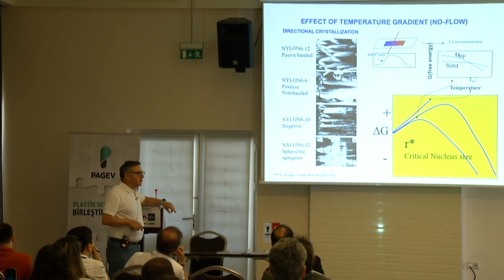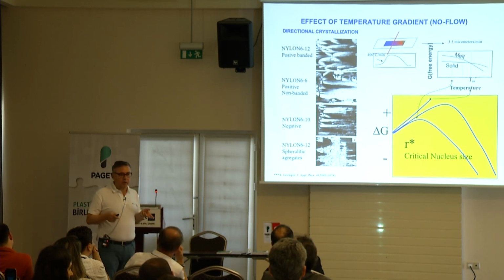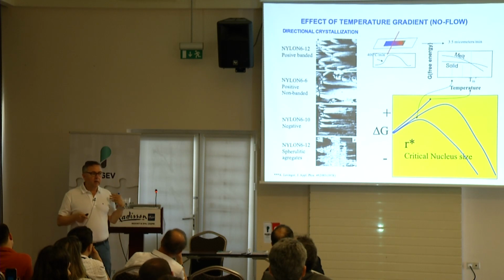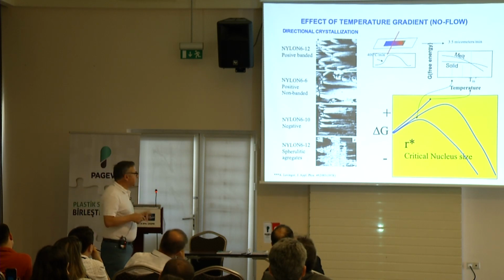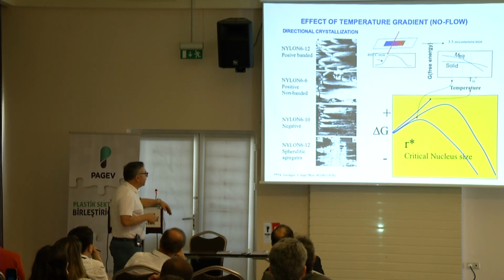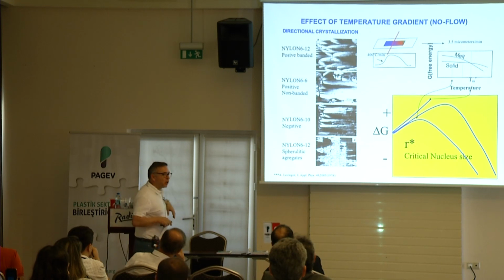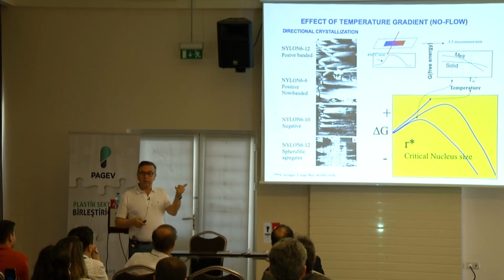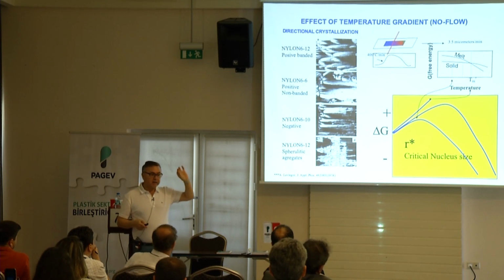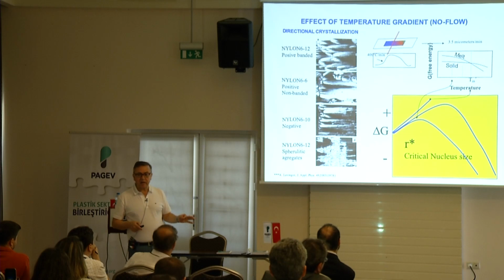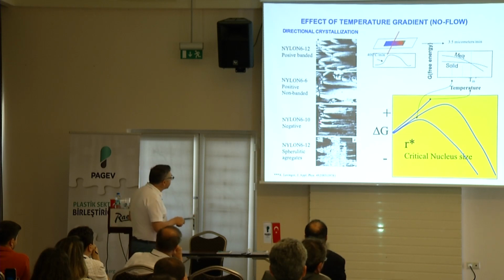So what happens is that the same effect that we told you earlier is also at play here: when the material is contacting a cold surface, delta T, right at the cold surface, your critical nuclei size dramatically goes down. Because the critical nuclei size dramatically goes down, you have so many of them.